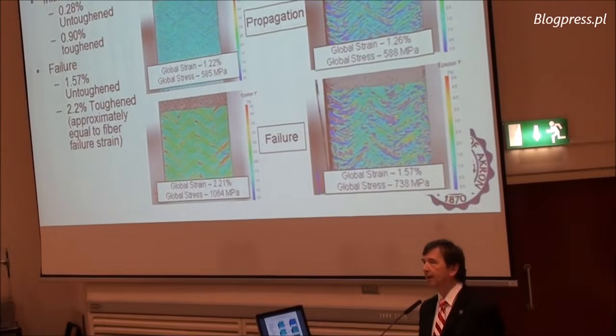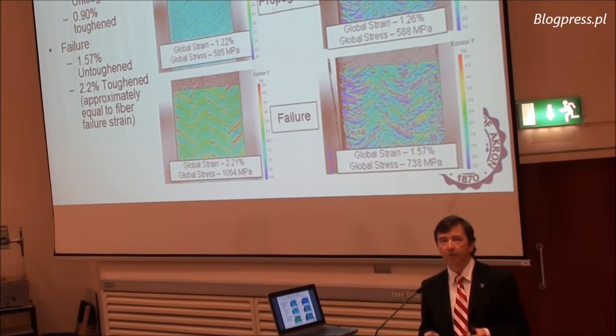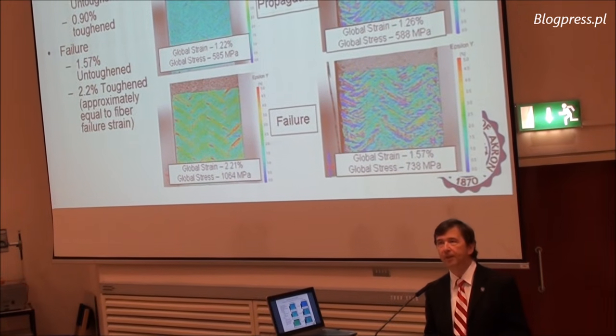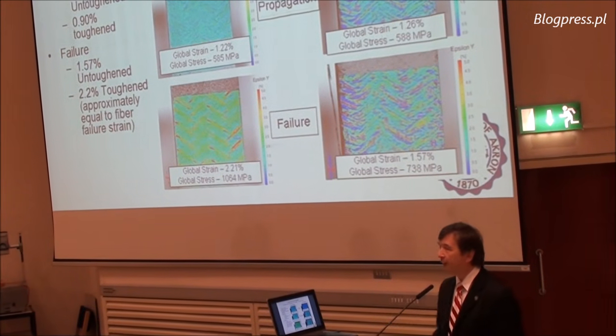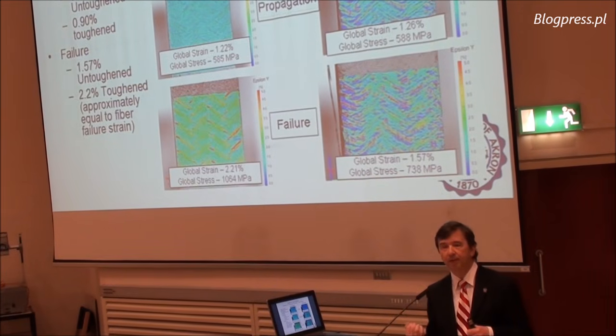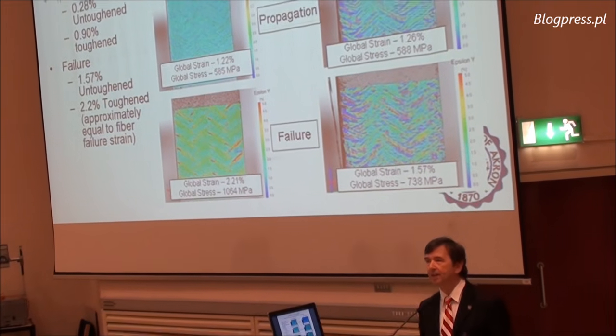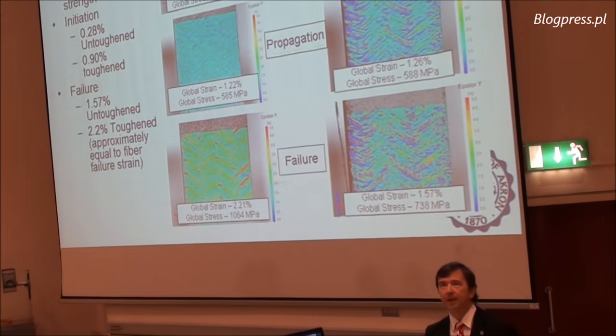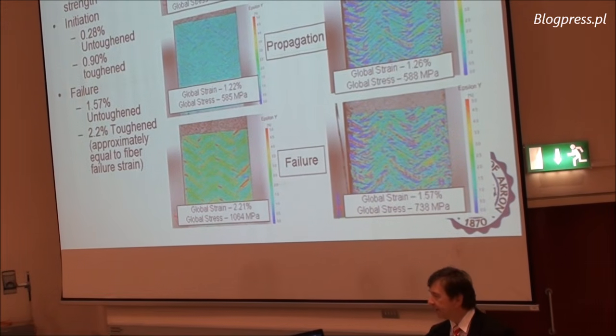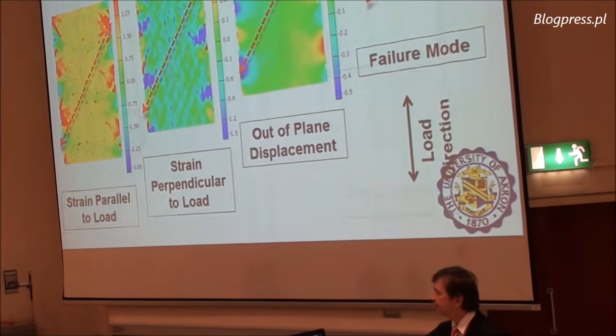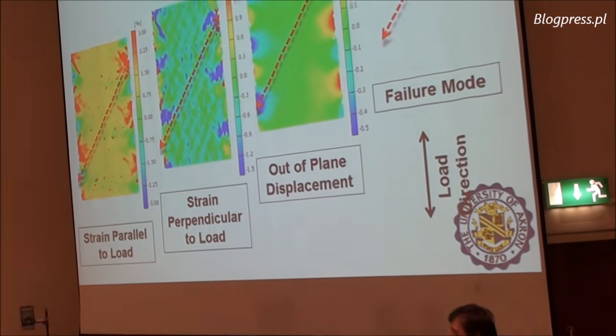We attribute that to the interface. We can have a material with a strong interface, that is on the left, and with a weaker interface, which is on the right. So although we combine materials that physically behave almost the same, because of the interface the effect could be quite different.